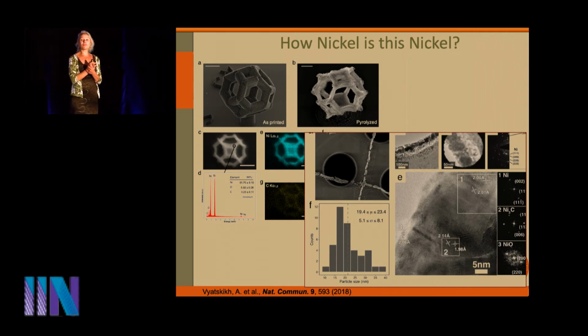Now, how many of you have used TEM before? So you know how challenging it is to prepare these samples, right? How do you convince an additively manufactured 400 nanometer beam to jump onto your TEM grid? It's not easy. So Andre was particularly ambitious and he said, well, I'm going to write a grid on top of a TEM grid, and I'm going to pyrolyze, and I'm just going to hope that one of these beams is going to subtend one of the holes. And sure enough, we got very lucky.